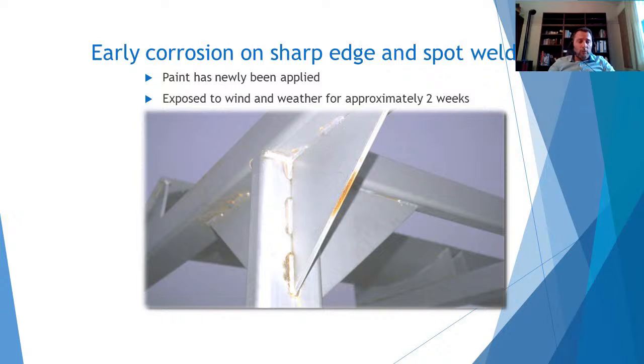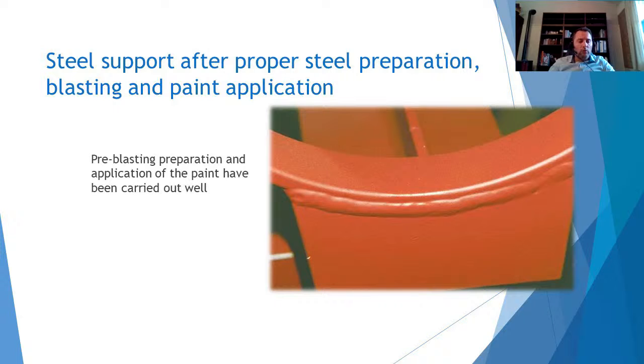This is a structure that has been newly coated and exposed for 2 weeks to the weather environment. You can see that the defects, the rust, the corrosion, start on the edges of the structure and the spot weld. Probably the edges are not completely rounded, and a continuous weld would be better to avoid this kind of problem. In this picture, we see a good weld seam and a rounded edge. So in this case, we have no trace of corrosion after several months.